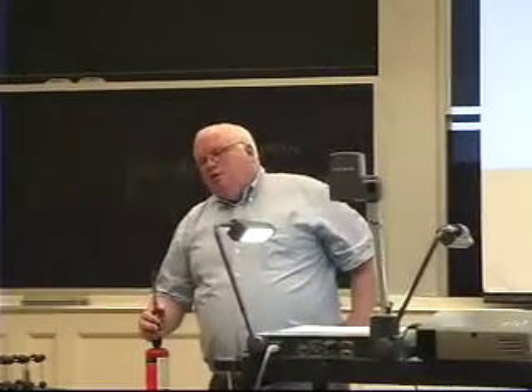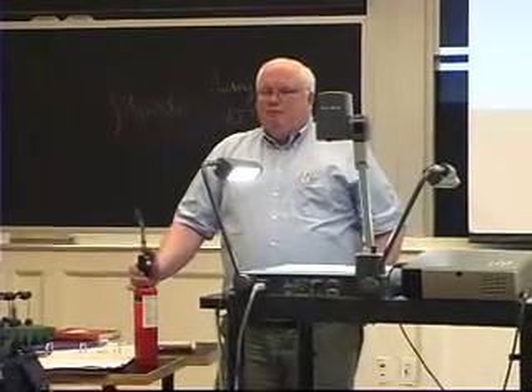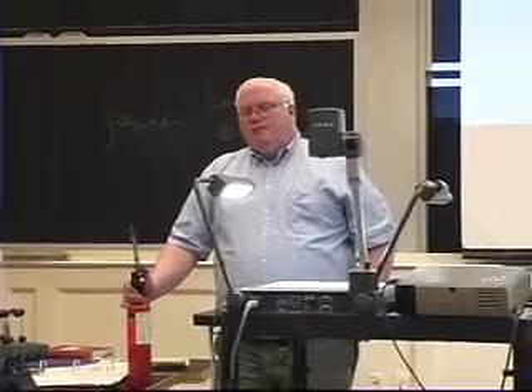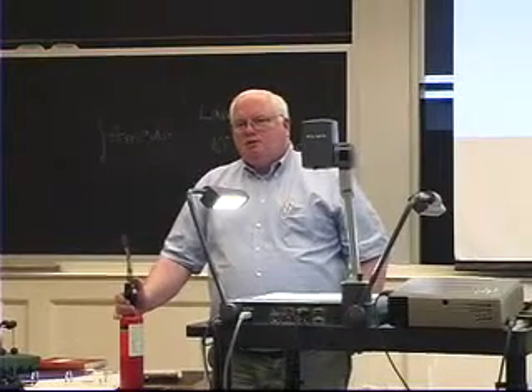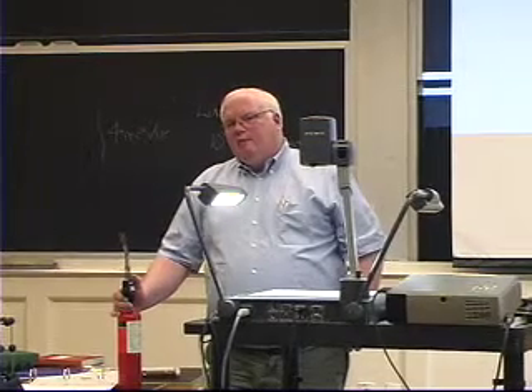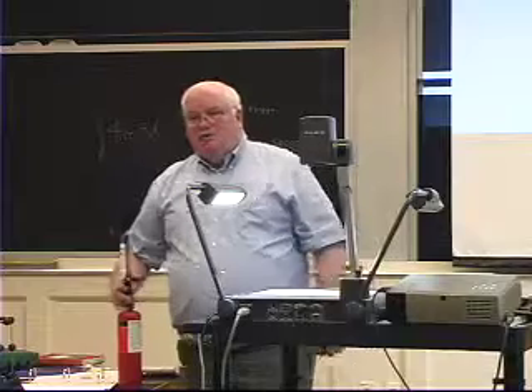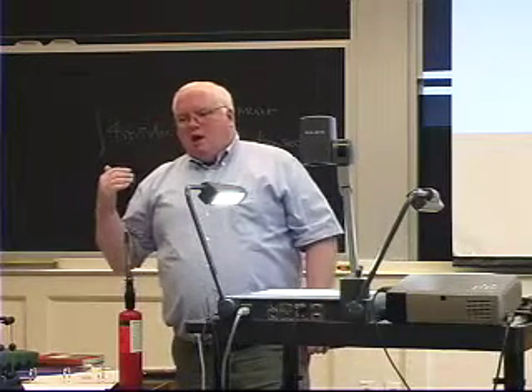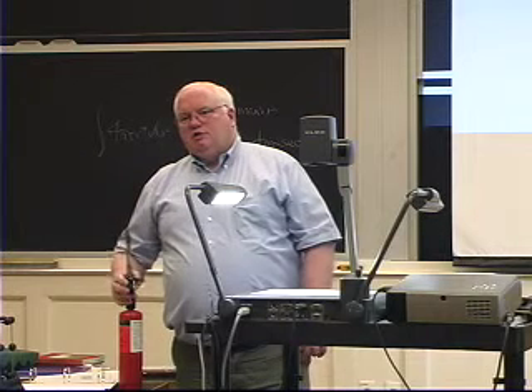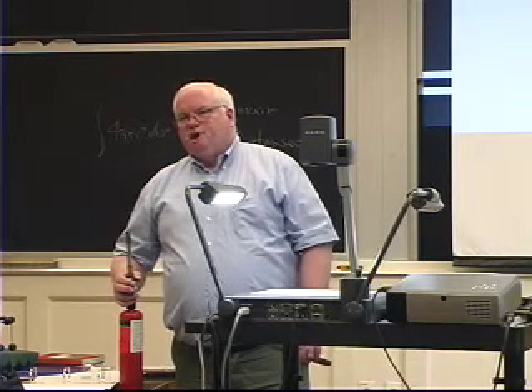I know you were a little fuzzy in the beginning of class with the definitions of everything, but if you had to define what cold welding was in terms of any types of parameters, is there any way to be more specific? Is it something below, let's say, 300 degrees C? And the reason I'll say cold welding is below 300 C is because you can vaporize off moisture contamination. The weak van der Waals attraction contaminants will be vaporized off at above 300 degrees C or so, if I had to pick a temperature. There's no fixed temperature, but cold welding is where I'm doing nothing to really get rid of the contaminants other than just trying to push them aside with pressure.